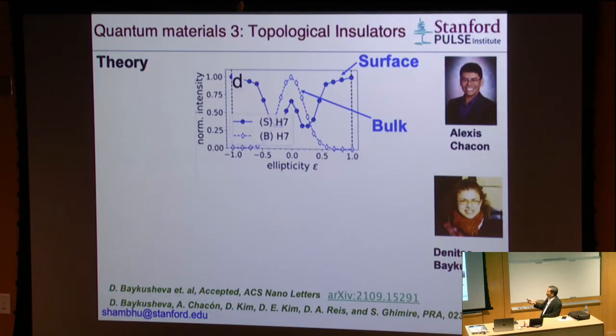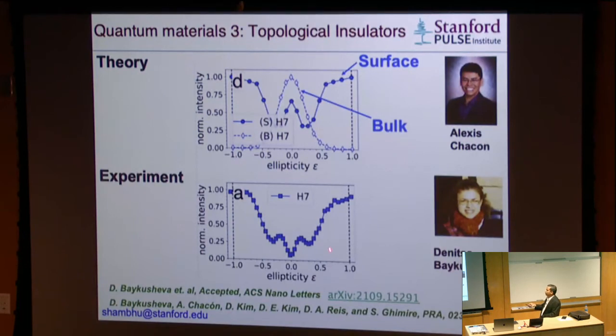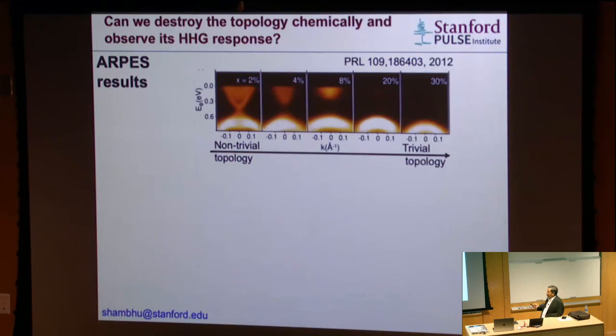Now let me show you the experimental results. These are the experimental results of using a really thin film of bismuth selenide, and the intensity of harmonic is plotted as a function of ellipticity. Pretty simple experiment again, and sure enough, you can see qualitatively, there are some details, this looks very similar to the emission that we expected from the topological surface states. There are lots of details here that you can read if you're interested. This was really excellent work. The experiment part was done by Denitsa, and the theory from Alexis. So now we have a signature, right? The signature of the topology is the dependence of the harmonic efficiency on circular polarization.